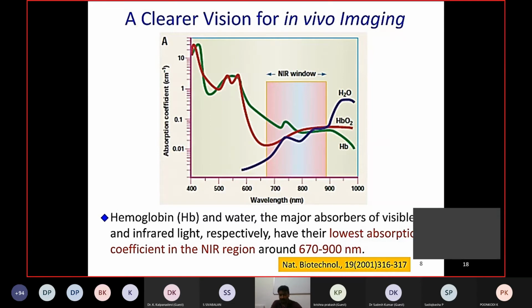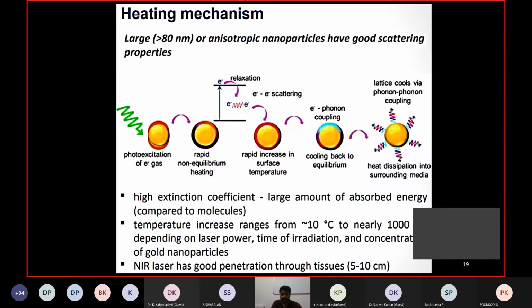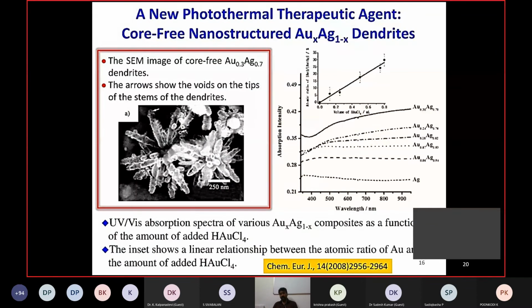The way in which gold heats up is plasmonic resonance, plasmonic heating. And the other materials, if you synthesize them, may heat by some other mechanism. They have a high extinction coefficient, so a large amount of energy is absorbed. That absorbed energy relaxes. Electron scattering happens, and electron-phonon coupling arises, and all these lead to the energy jumping between states and then relaxing, and you get the excess energy released in the form of heat. And NIR2 or NIR1 radiation have better penetration ability compared to UV radiation. NIR2 penetrates even better. The longer the wavelength, the better the penetration.